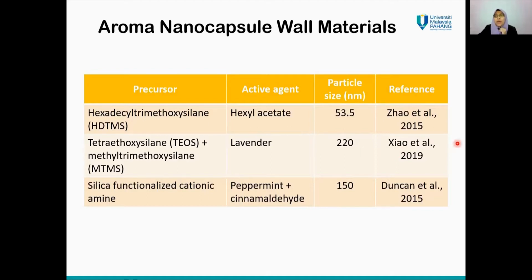In organically modified silica via the sol gel approach with the average particle size of 220 nanometers. They use tetraethoxysilane and modified with methyltrimethoxysilane to enhance the mechanical strength and compatibility of the wall material. And the encapsulation efficiency obtained was 96.36% under the optimal conditions. And the last work was done by Duncan et al.